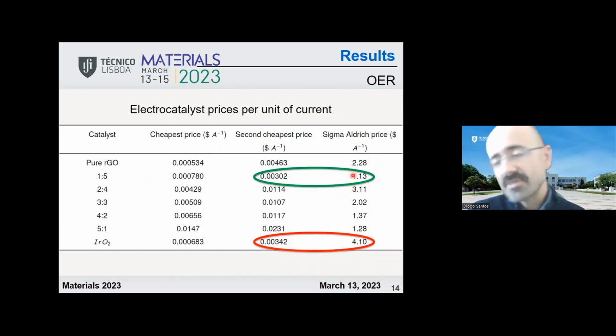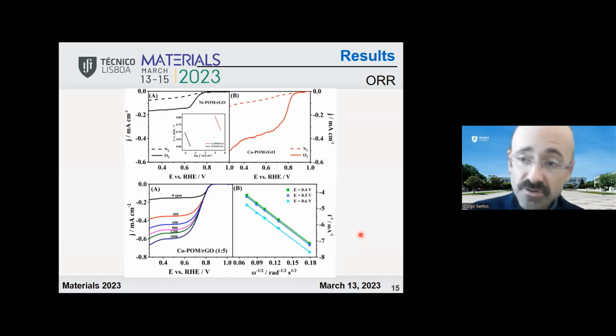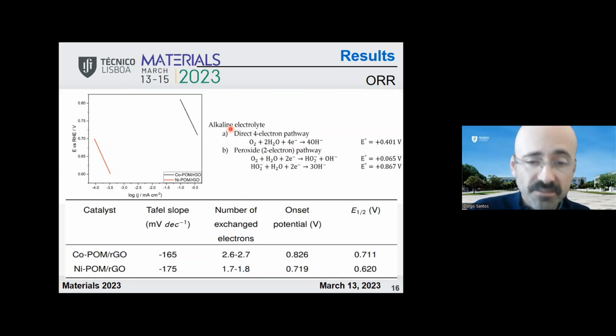Basically, if you consider the prices also, from Aldrich, for example, the material that we tested is much cheaper than the iridium oxide if we consider their performance. We also tested for the oxygen reduction reaction, and for the oxygen reduction reaction, nickel POM has interesting results, but cobalt POM was even slightly better. So these two materials that had been the best for oxygen evolution reaction were also both good for oxygen reduction, cobalt POM being the best one.